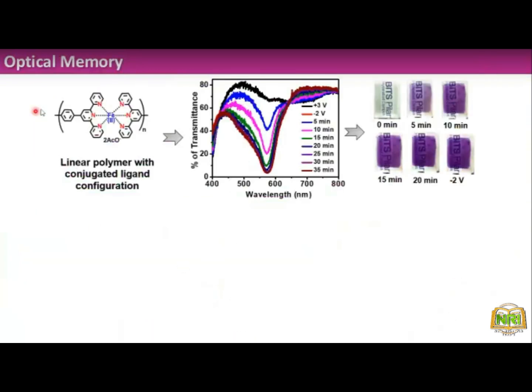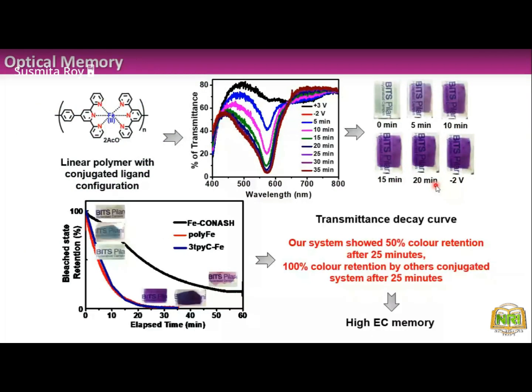Another comparative study we did is a normal one-dimensional polymer film. First, the same thing happened: in 20 minutes it almost completely changed its color. So now we have taken the 3 data sets and compared them. The image is not clear here, I guess, but we have seen that while other materials come back to their original state in almost 20 minutes, ours can return only 50% of the color in 20 minutes. That means we can say our system shows almost 50% color retention, right? So that means it has high electrochromic memory compared to other reported conjugated ligand, famous ligand, polymer, ligand metal polymer.